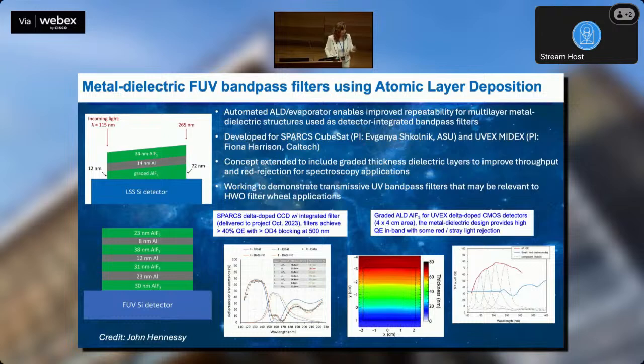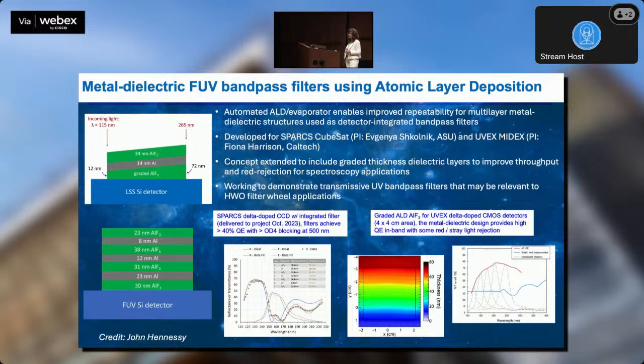For SPARCS, I see Evgenia sitting here as the PI of SPARCS. We developed a 2-channel camera and delivered that. Hopefully SPARCS will be launched soon. And we used these filters that originally were developed for a DOE project, Department of Energy project, but we really honed in on this and made it for the far UV detector of SPARCS. And now for UVEX, which is the current MIDEX in phase B, we are developing those filters for the long slit spectrometer with a graded profile. John Hennessy has done a really nice job of making this work to get nice in-band efficiency and some suppression of the scatter.